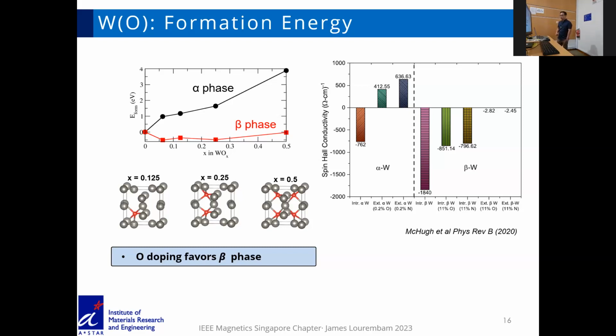And this is the spin Hall conductivity determined for various tungsten systems. This bar here is for pure beta phase tungsten in the theoretical calculations, and if one keeps on increasing the oxygen, for example at 11%, it drops significantly. As one increases the oxygen doping further, the spin Hall conductivity drops as well. So one would just put in a little bit of oxygen to stabilize the beta phase, but not reduce the spin Hall conductivity too much.